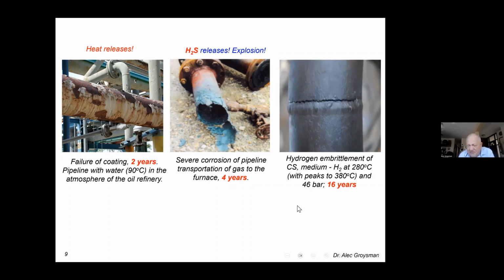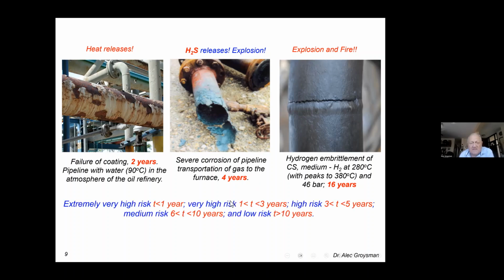The third event, as you see, was hydrogen embrittlement of carbon steel, and the medium was hydrogen, gas is hydrogen at 280 degrees centigrade with peaks to 380 degrees and 46 bar. After 16 years, hydrogen embrittlement occurred with explosion and big fire at the oil refinery. As you see, after 2 years, 4 years, and 16 years.